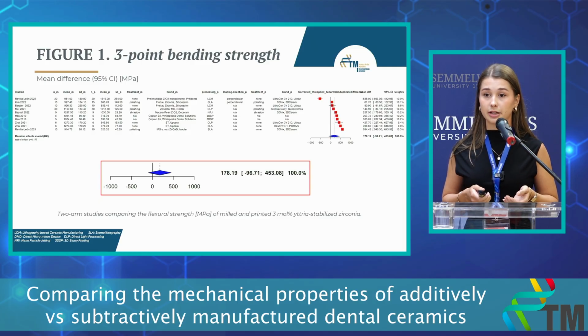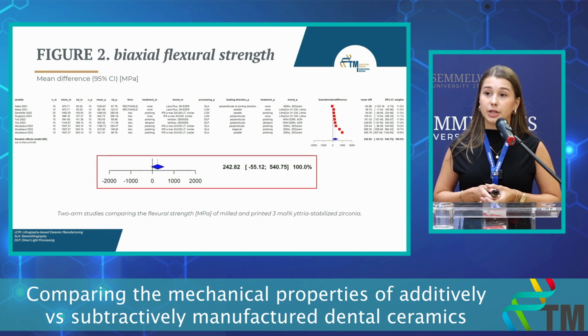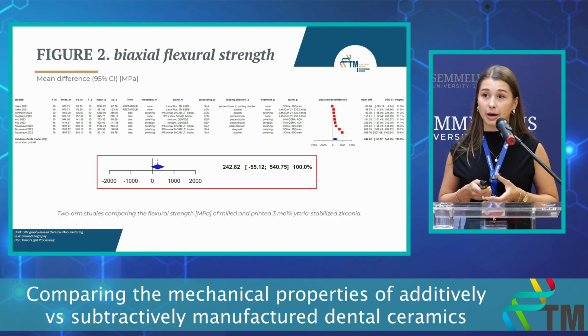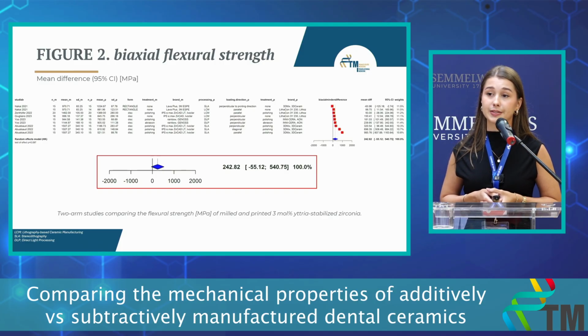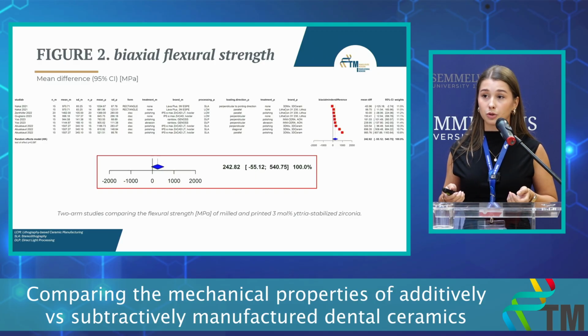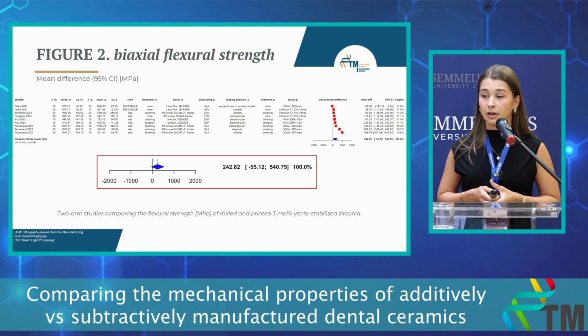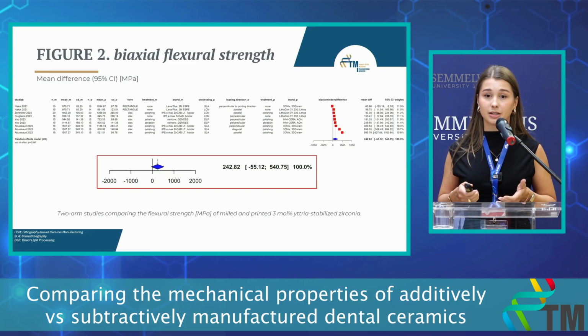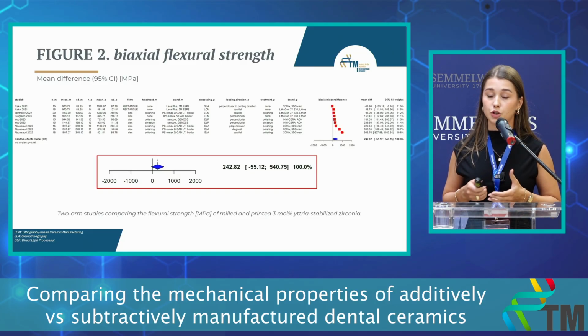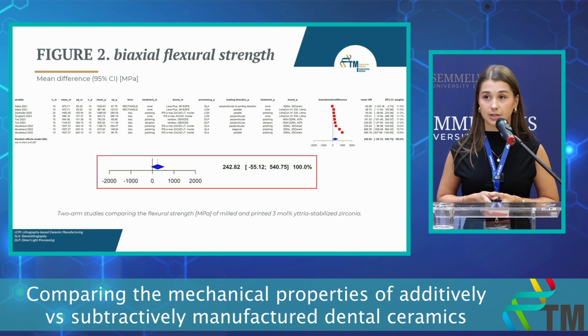And although printed materials have come a long way and are closer and closer to milled materials, there's still room for improvement, and we believe that they shouldn't be applied in the same indications yet. We can see a higher mean difference value for the 2 arm studies comparing the biaxial flexural strength of milled and printed zirconia, but the conclusion is the same. Although the results did not reach mathematical significance, the difference emphasizes that printed zirconia did not yet overcome milled zirconia, and that they shouldn't be applied in the very same indications yet.